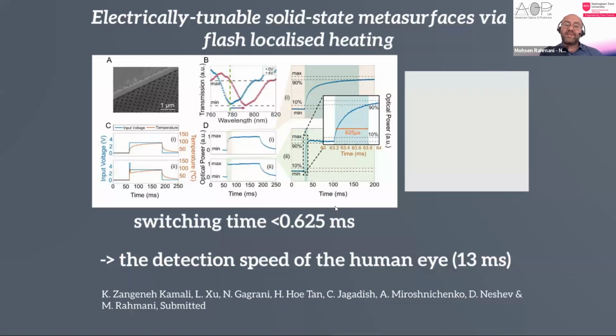Here you see that we are electrically changing the frequency, and as you see, I have a very nice control on the frequency here. What you are seeing at the moment is not noise. It's just very fast on and off, which our eyes cannot see. So it is very groundbreaking research by combining all of this different understanding, thermo-optical effect of silicon, using local heater,